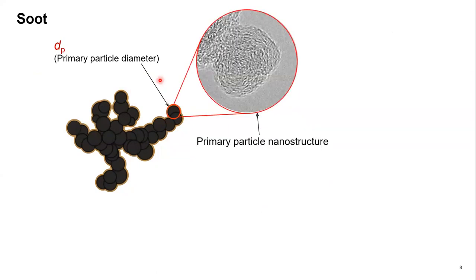I'm going to take a minute to define a few terms that we're going to be discussing throughout this presentation. So soot are these agglomerated structures of primarily spherical primary particles. And within a single primary particle, there is a nanostructure, which is basically layers of graphene stacked upon one another. So together, the primary particle diameter and the nanostructure of the primary particles influence the toxicity of the particles, their oxidative potential, and how they interact with light.